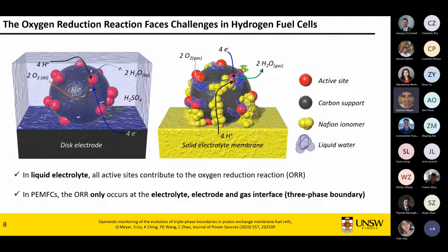So now, looking at catalysts for the oxygen reduction reaction, the first step is the rotating disk electrode, or RDE. When you're in a liquid cell electrolyte, it's a very much optimized system. You have an infinite proton source because you're saturating an acidic electrolyte. You've got your electrons coming from your disk electrode. You've got an infinite amount of dissolved oxygen. So it's quite a good system to work with.